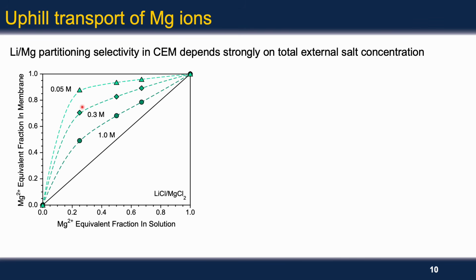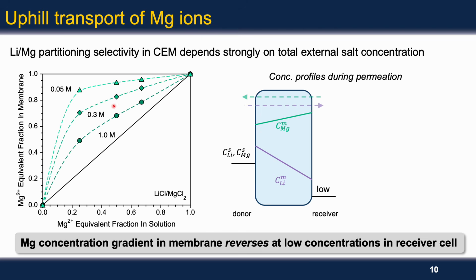And so what does this mean for our permeation experiments? Well, here we start with pure water in the receiver cell at the beginning of the experiment, but as salt permeates across the membrane, this turns into a very low concentrated salt solution. And so the preference for magnesium ions at the receiver side of the membrane can be exceptionally high, so much so that it can reverse the internal concentration gradient, such that magnesium ions transport from the low concentration side to the high concentration side, and this is uphill transport.